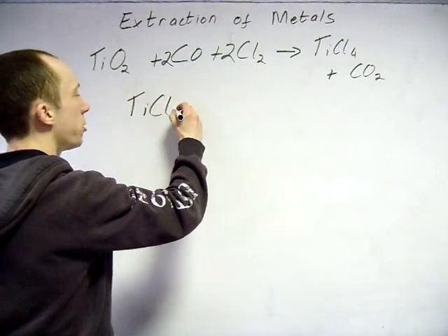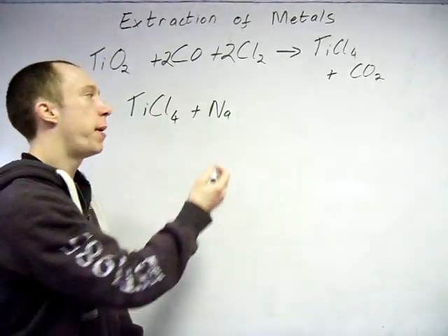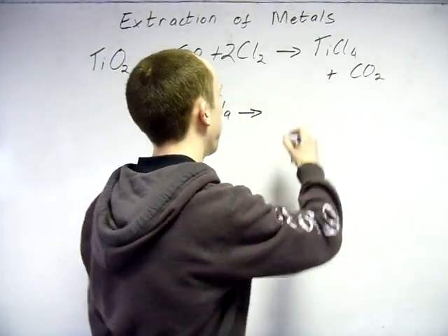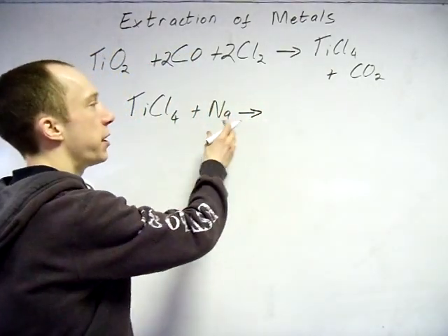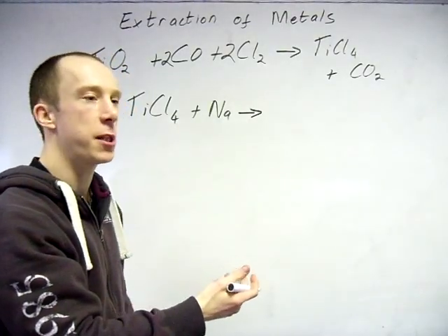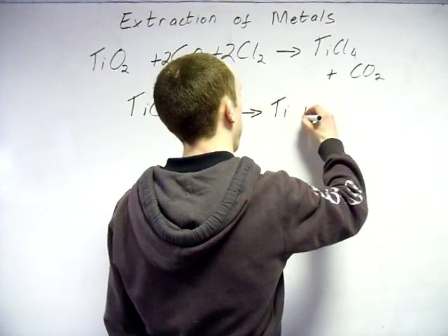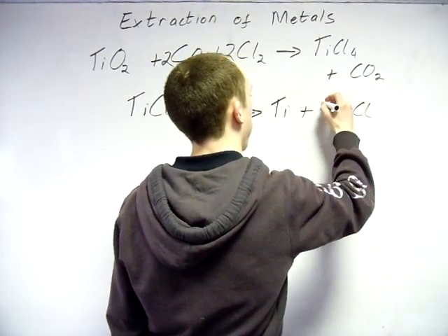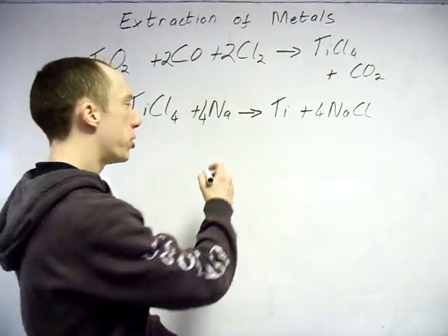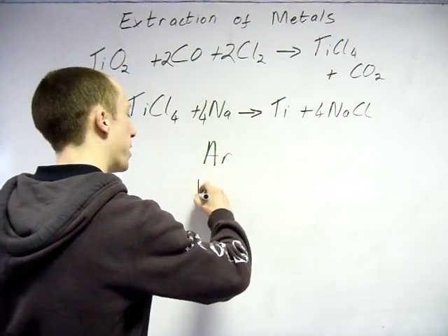Now, when we've got our titanium chloride, any more reactive metal, sodium, magnesium, they're the favourites. Just be careful if you use magnesium, obviously you're going to get MgCl2 rather than NaCl, which we'll get here. Now, this must be done in an argon atmosphere and at high temperatures.